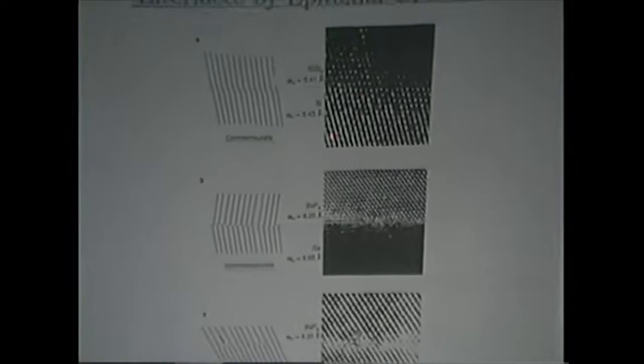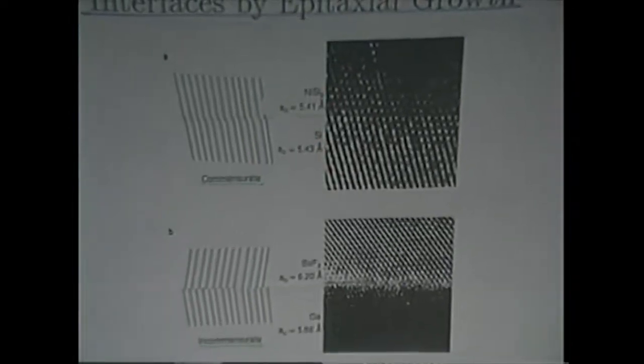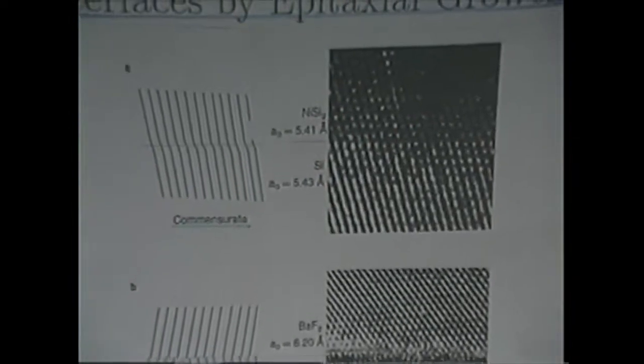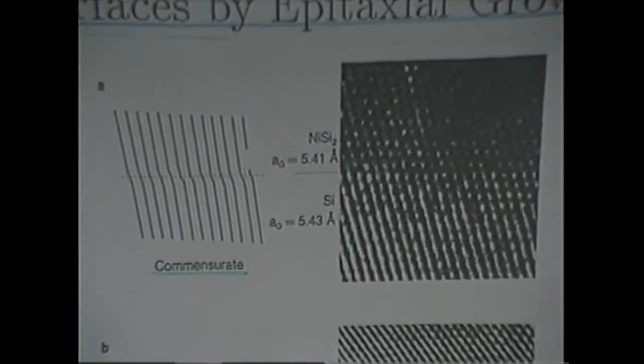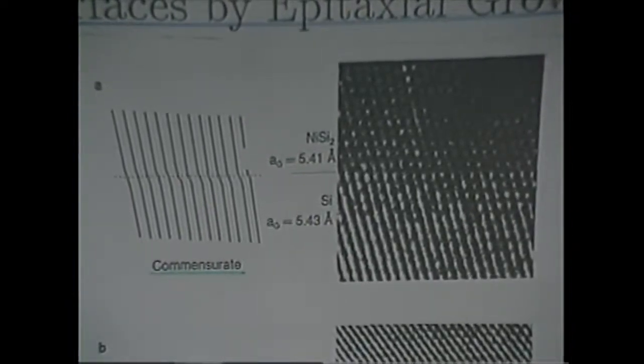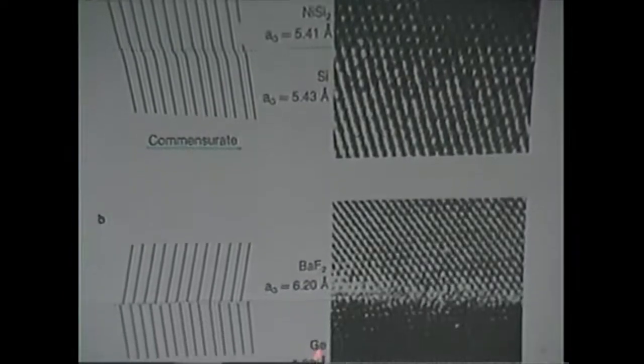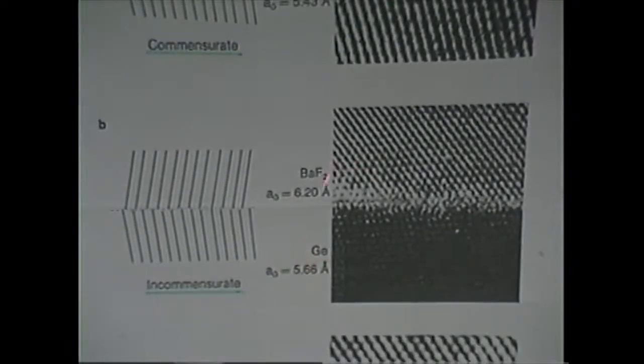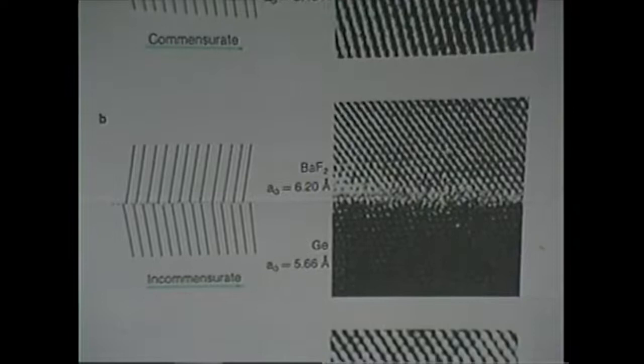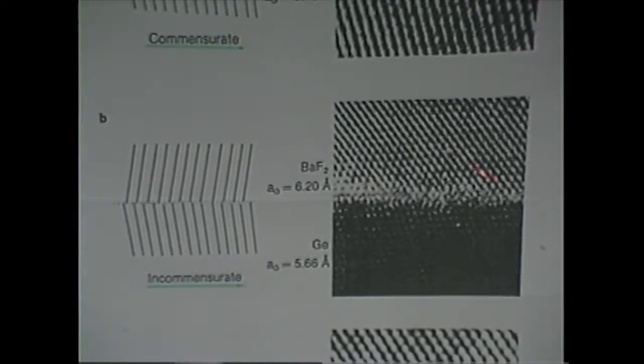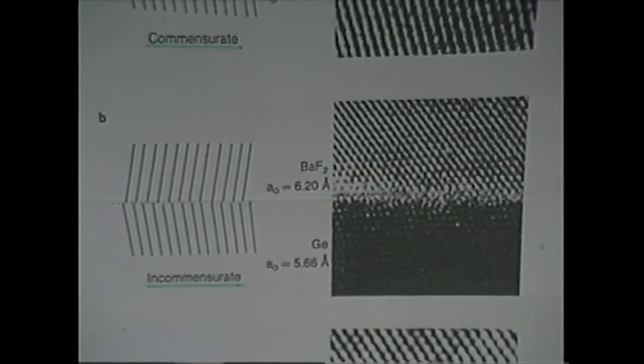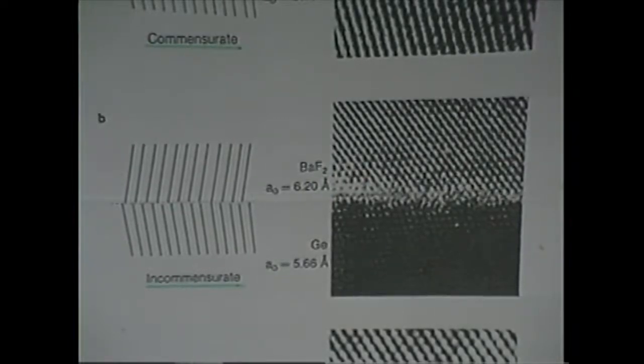Just to show you how things are in molecular beam epitaxy, here's the case for the semiconductors. So here's silicon, and here's nickel silicide. Now that forms a very nice commensurate structure, very much like potassium on graphite. But here's a situation of an incommensurate structure of germanium with barium fluoride, where the lattice constants are sufficiently different that you don't form a nice interface, and the interface is mushy and corresponds to several atomic distances.